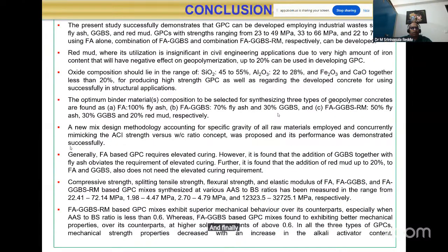And finally, what I want to conclude is, first thing, the oxide composition of the material we are using is important. Next is the molarity of the sodium hydroxide we are using. Then the sodium hydroxide to sodium silicate ratio we are using. Then the combination again varies with the oxide composition of the material we are using. Then I can say that with increasing the S to B ratio, obviously the strength is decreasing, and for all the mixes, similar to normal concrete, we cannot use the empirical equations blindly that we have for normal concrete.